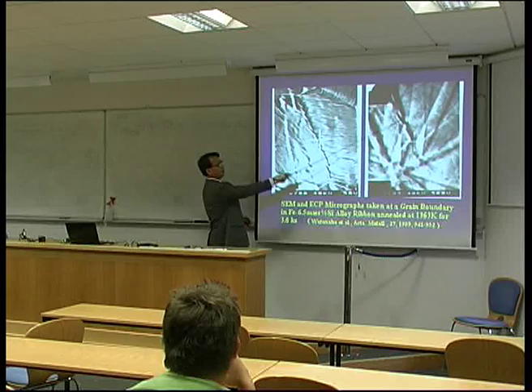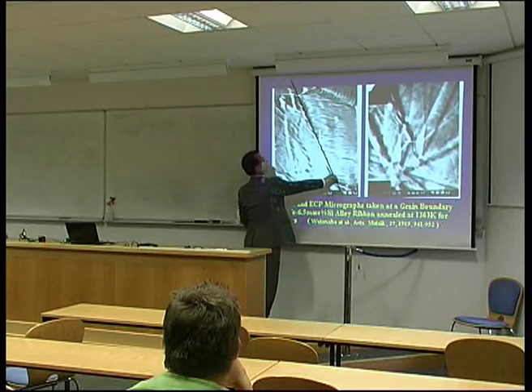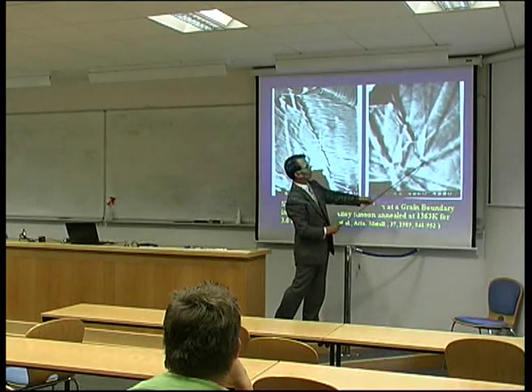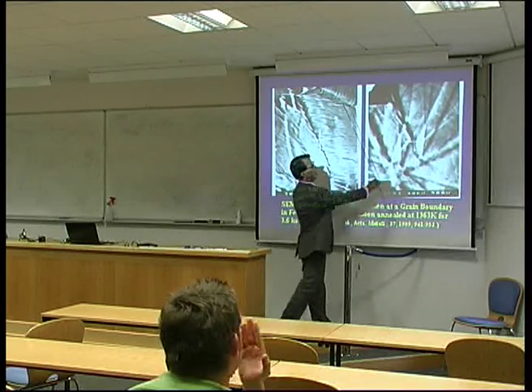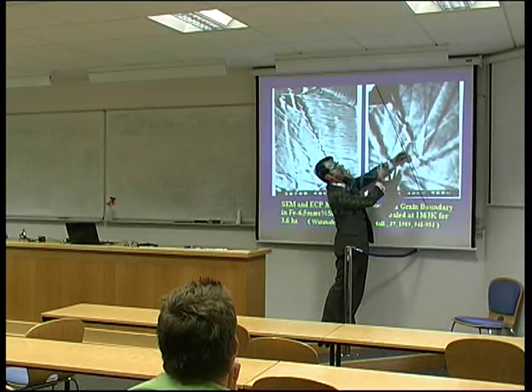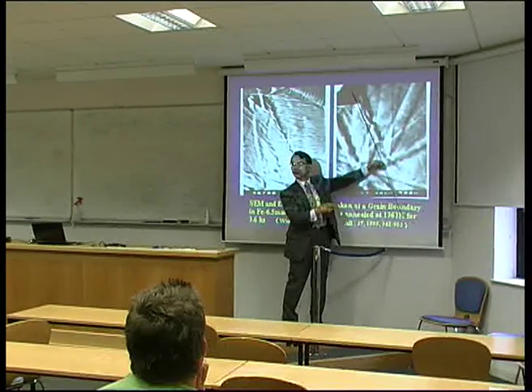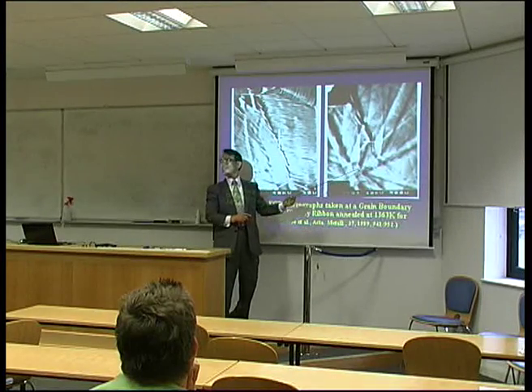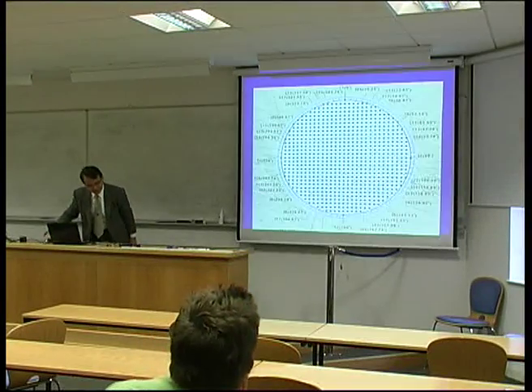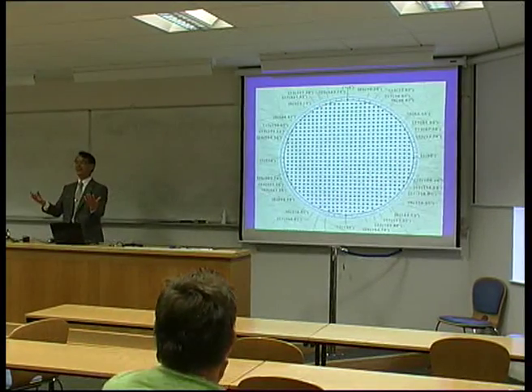So, for example, this is the same image, and this is the ECP image. Here is the grain boundary, and then you can see this pole moves to this pole, up to this. This means about 10 degrees. So, here is the grain boundary. This means two crystals are relatively rotated by 10 degrees from this. So this is the tilt part. So we can image it.